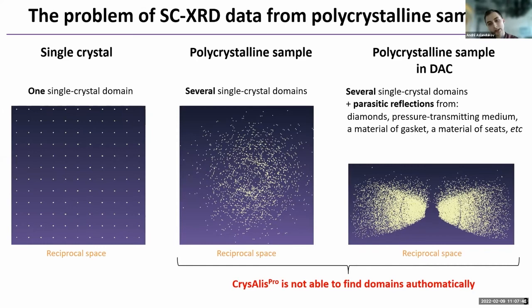Now the crystallographic packages for single crystal data processing, such as CrysAlisPro, work well with single crystal X-ray diffraction data obtained from normal single crystals. But in the case of polycrystalline materials, where step scans contain diffractions from several crystallites, such programs are not able to find the unit cell to work with. This situation is even more complicated in the case of high pressure studies in laser heated anvil cells, where we have a lot of parasitic reflections from diamonds, pressure transmitting medium, and so on.